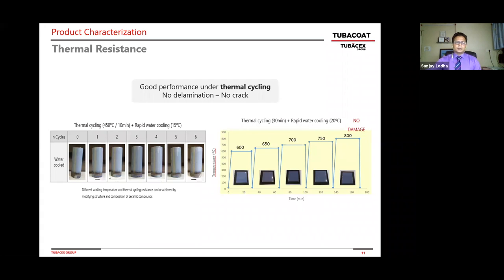In any refinery or petrochemical process, you have startups and you have shutdowns. You have rapid heating and rapid cooling. Just like your online spalling in a delayed coker, or if you have a steam air decoking, or if you have a pigging, but at least the first two, where you have a thermal shock, expansions and contractions, that's where this property comes in very handy. So what you see on the slide is we take the thermal cycling up to 450 degrees Celsius, close to, I would say, 850, 900 degrees Fahrenheit. And then we do a rapid cooling and we do many, many cycles over.